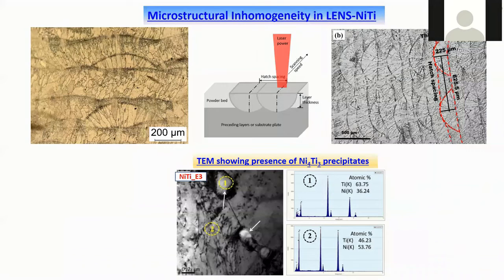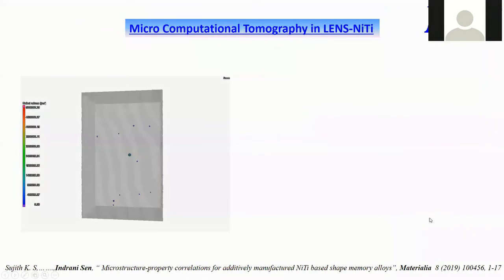Not only that, based on the laser energy density, we have also noted that the one produced with the highest energy density is producing some precipitates in the alloy. Okay, so although we started with the same powder composition, different processing energy can lead to the formation of different phases. So that is how we are changing the microstructure also.